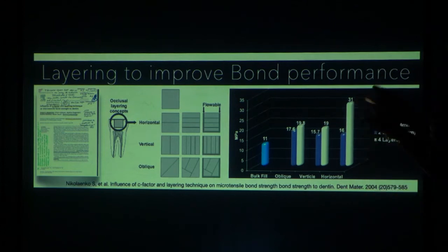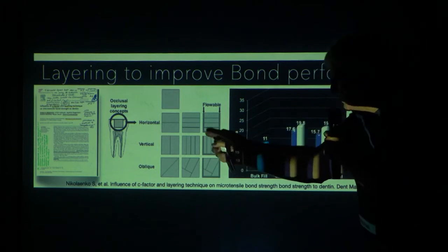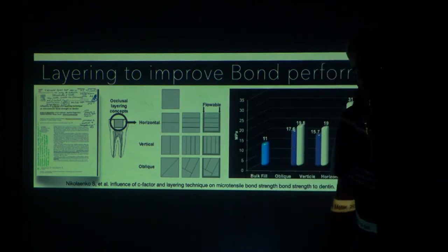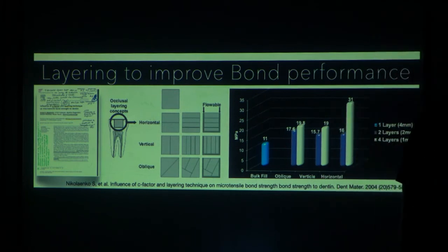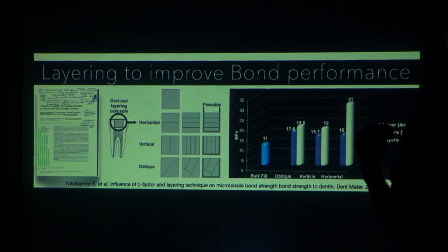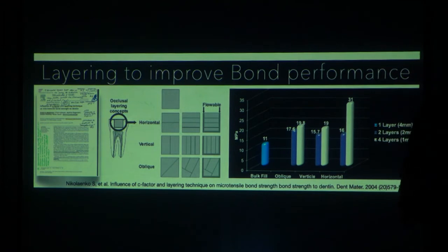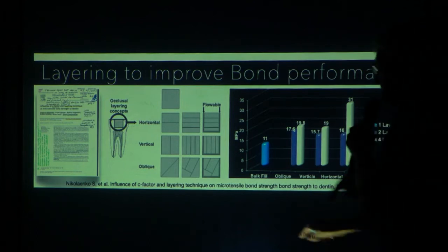But this idea of 30 being a key number in an in vitro test, again, validated the idea that you can get a bond strength to dentin that is as strong as the cohesive strength of enamel. In other words, if you pull enamel apart, it takes 30 megapascals to pull it apart. In this restoration, to pull that 1 millimeter layer of composite off the tooth takes exactly the same amount of stress as it would take to pull enamel from itself. So that's called biomimicking or biomimicry, where the bond strength to dentin is the same as the cohesive strength of enamel. And 30 can be increased if we make these layers even thinner.